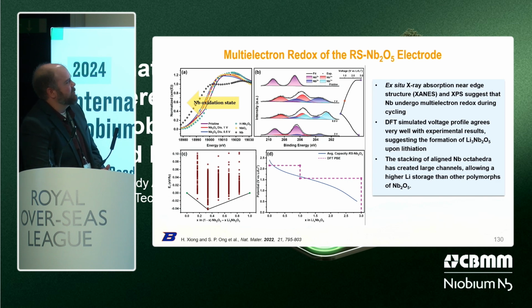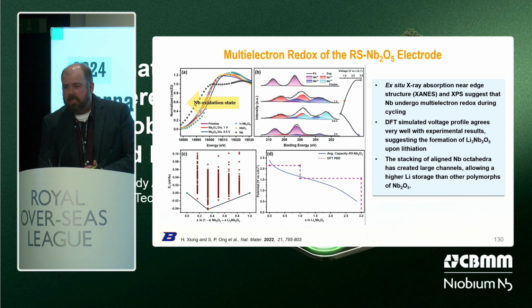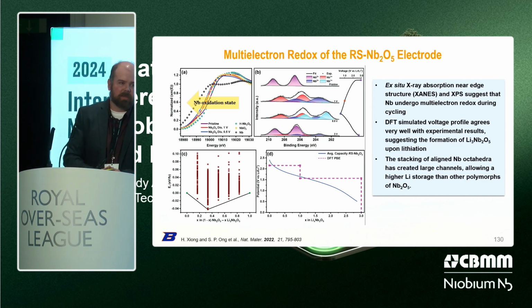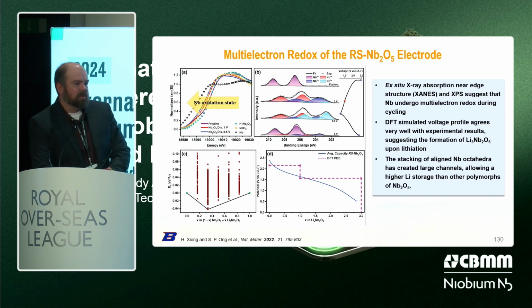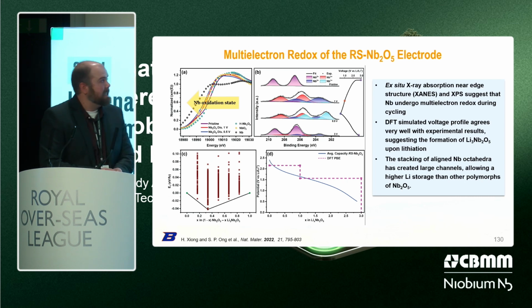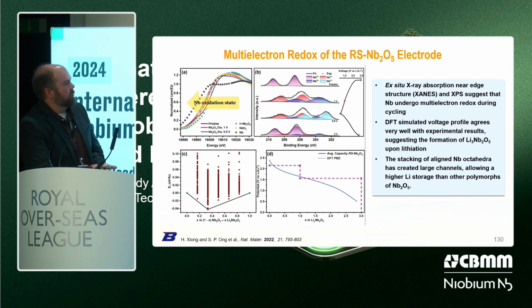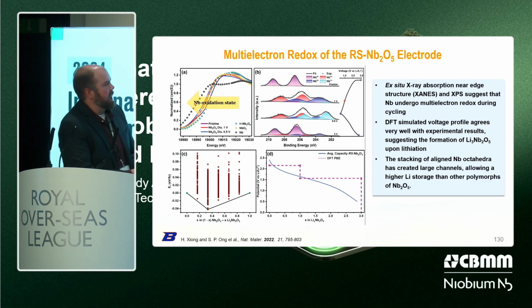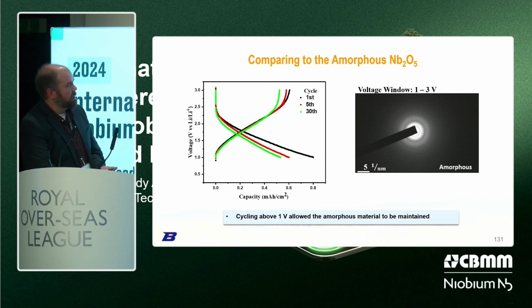We were able to use XANES to see that the niobium oxidation state at a full discharge was a lot closer to having 3 lithiums inserting into Nb2O5 rather than just 2. That's why we were getting such high capacities compared to what theoretical would have shown. And DFT simulations actually proved that this is pretty accurate. You're seeing here the voltage profile in conjunction with a DFT simulation of where we would see lithium in this Nb2O5 structure. We came out pretty close in capacities for that full lithiation.